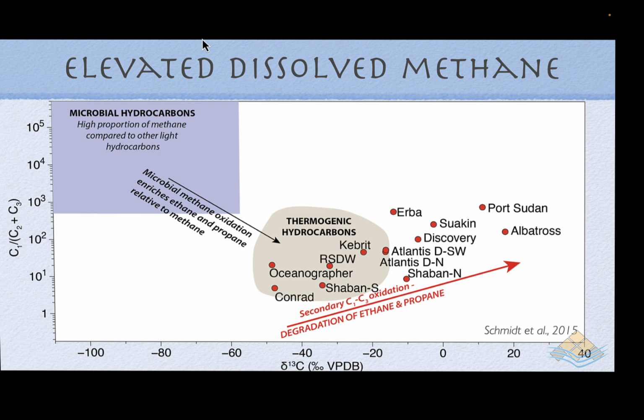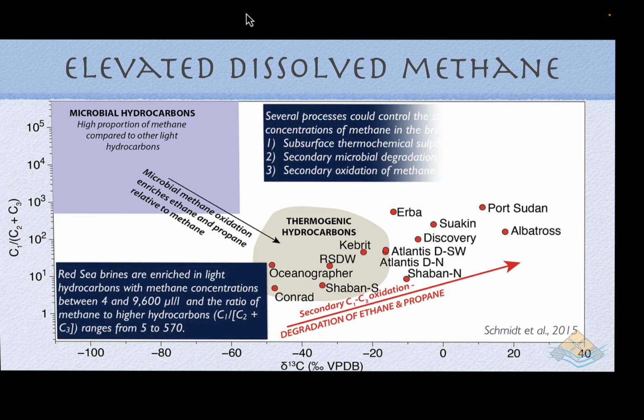We do see degradation of ethane and propane, but what's interesting here is that the ratio of methane to the higher hydrocarbons, the C1 to C2 plus C3, is in the range of 5 to 570. It's underlining the very likely thermogenic origin for a significant proportion of the hydrocarbons dissolved in those brines.